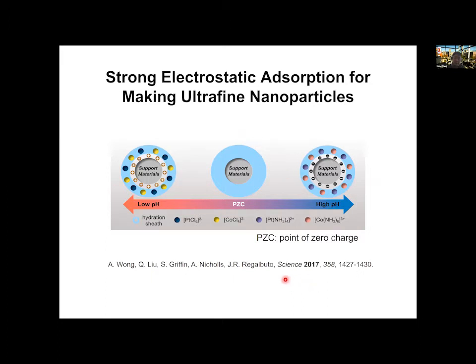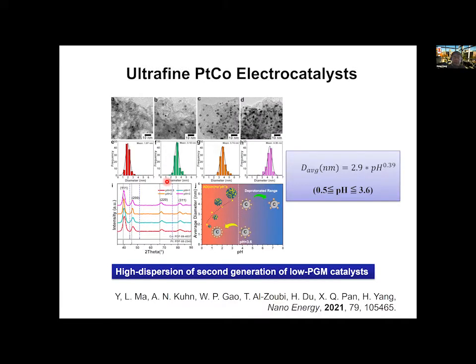us to look back at one of the recent studies on the synthesis of ultrafine metal and metal alloy nanoparticles. So what we have designed, based on the design principle, is to check whether we can tune the solution phase processing right around the so-called point of zero charge, and hopefully sufficiently solvate the carbon support. This would allow us to attract both the platinum and non-platinum metal precursors to form hydrated layers, improve the density of the particle formation, and further anchor the platinum on the substrate.